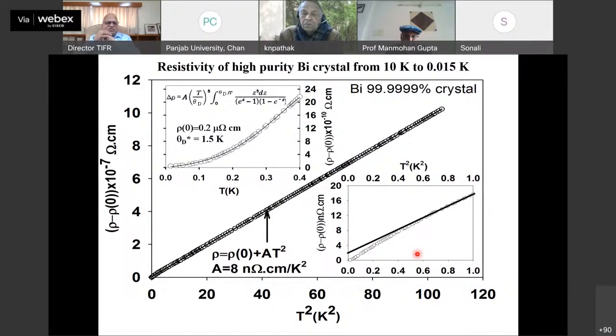So everybody said, as I said, initially the transport, the resistivity goes to zero. The resistivity is not so easy to measure. As you can see, this is our latest measurement, down to 15 millikelvin. Nobody has measured below 20 millikelvin anyway. So the point is that the resistance is extremely small. It's of the order of nano-ohms. So when you have something which is at nano-ohms, you can't pass large currents either, because the cooling power at the microkelvin is extremely small. It's about 5 nanowatts. So the point here is that you cannot use conventional methods.